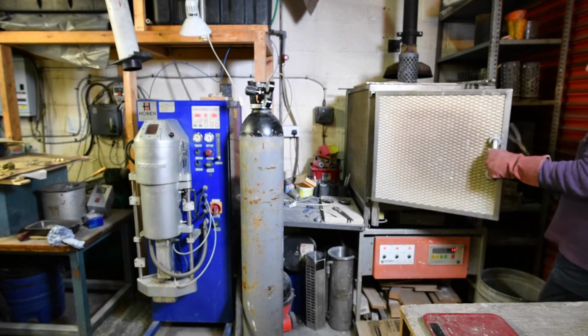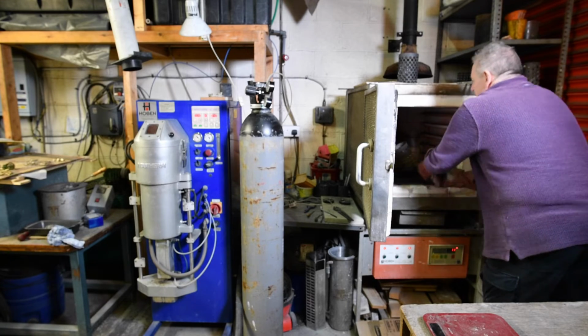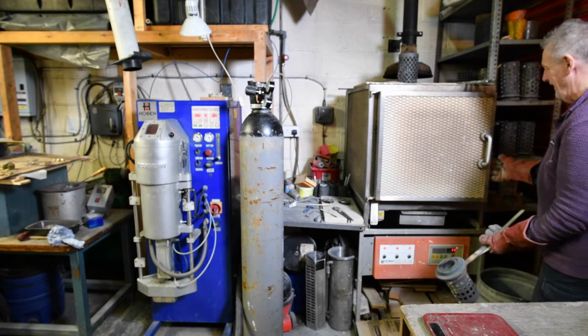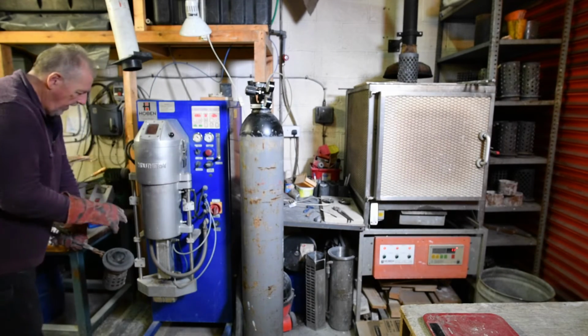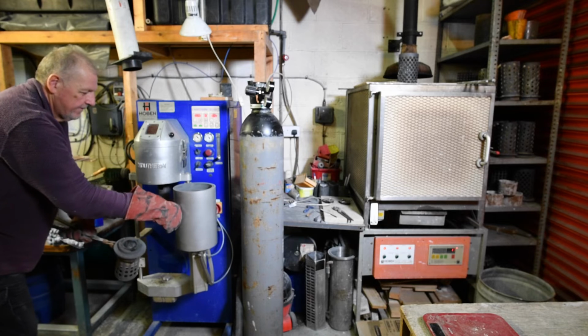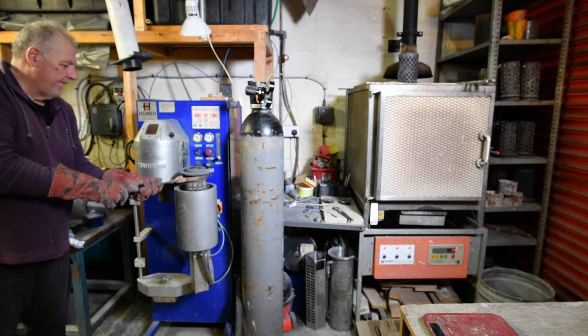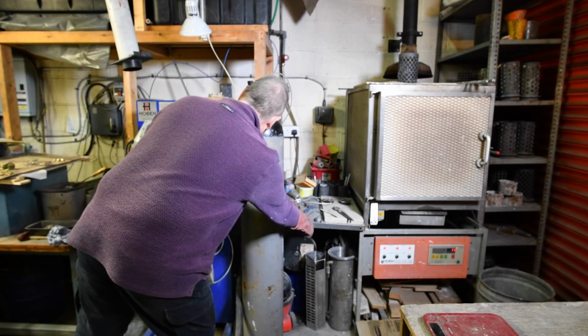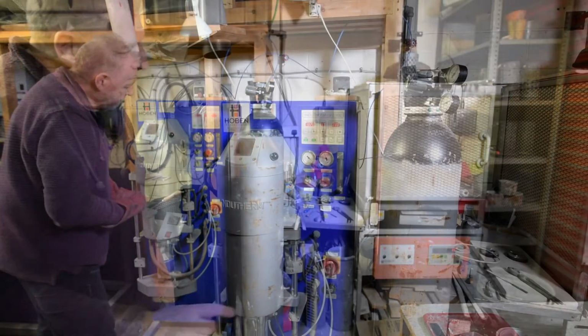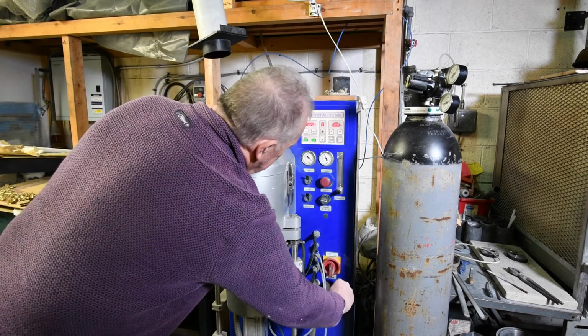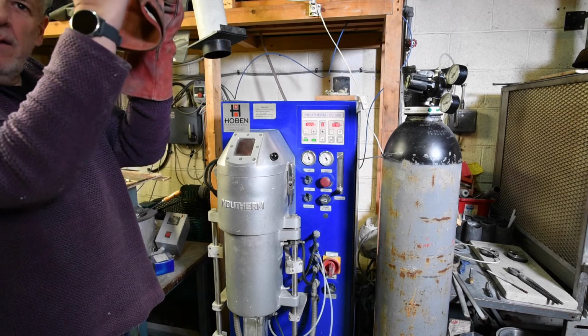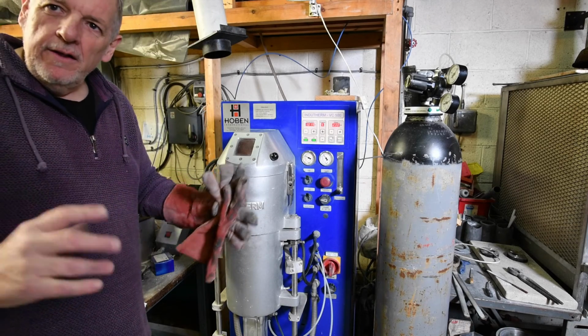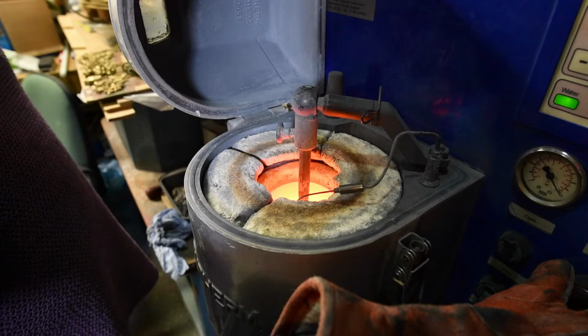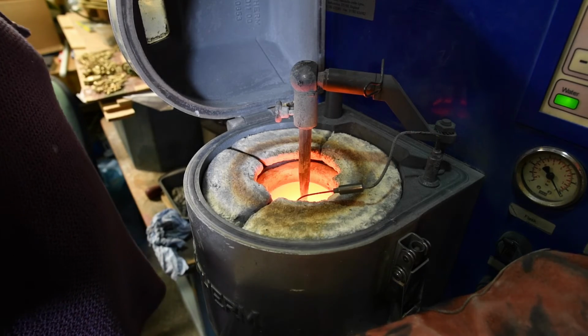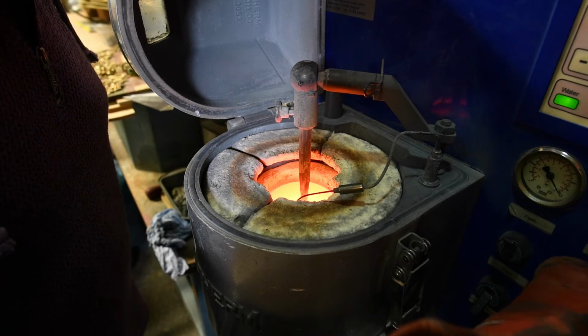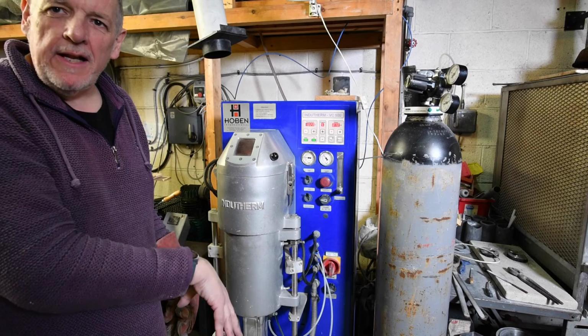Right, we've got to the kiln, to the flask. Bottom chamber. The flask then goes into here. Lifted against the bottom. Watch this gauge here. This bottom chamber is then put under vacuum, so that when the metal goes in, the vacuum assists it to fill the nooks and crannies in that rod. Then we turn this knob, which raises the rod, frees the metal to go into the flask. Then we can close that rod once again to put the next charge of metal in for the next cast.